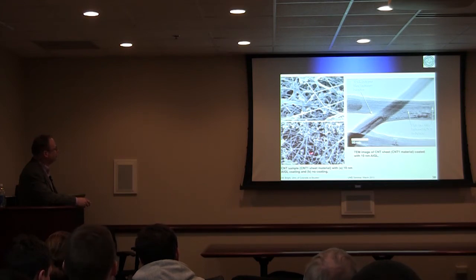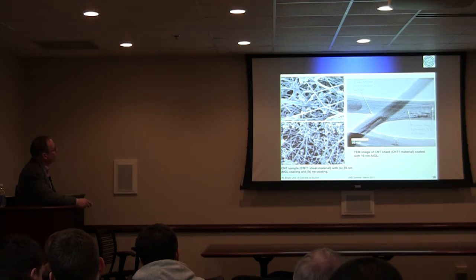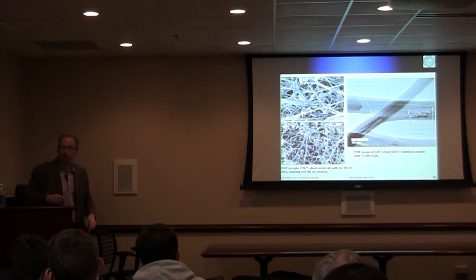So this is the material itself. This is reverse. This is material itself without coating. This is material with coating. The amount of coating is 10 nanometers MLD. You take a close look at this, see how wonderful the process is. Not only does it interlock individual nanotubes when they cross, but it actually permeates into the actual fiber.